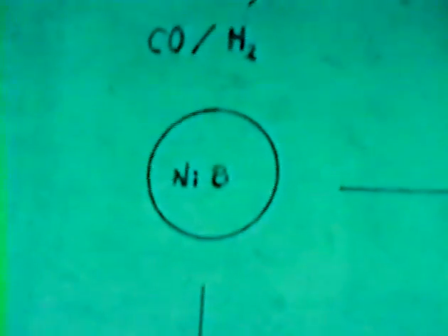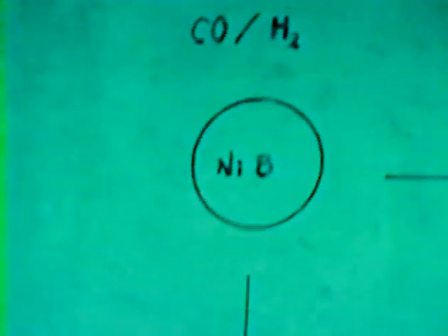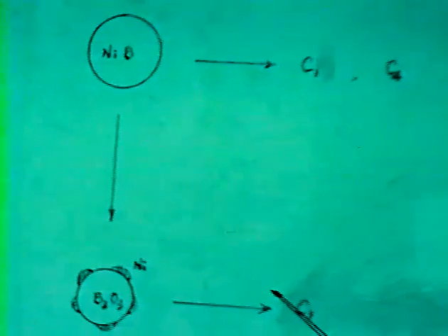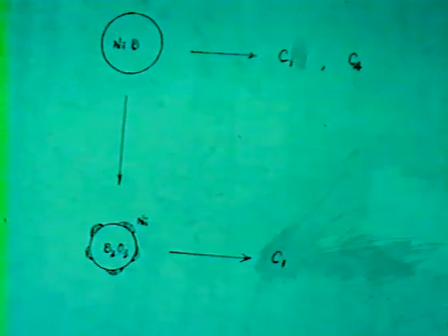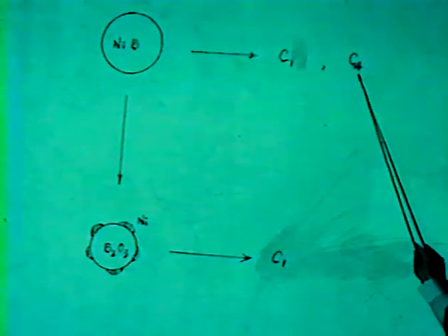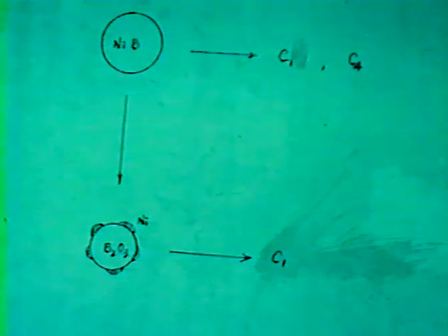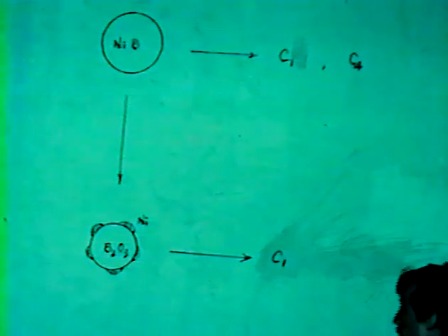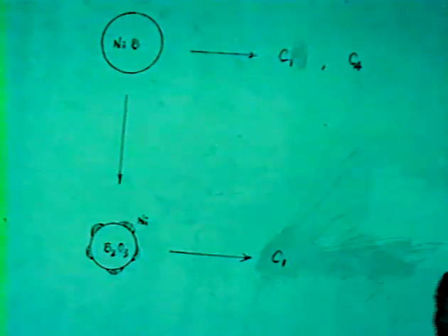hydrogenation of carbon monoxide on amorphous boron alloy particles produces mainly C4 hydrocarbons other than methane. The reaction results in crystallization and segregation. After segregation and crystallization, the catalyst is a methanation catalyst for CO hydrogenation. Therefore, to maintain the high selectivity to C4 hydrocarbons, it is important to keep the amorphous structure stable. This work was done successfully in our laboratory with the incorporation of phosphorus into the boron alloy. I will report these results next time if possible. Thank you for your attention.